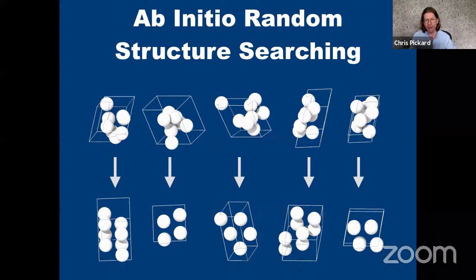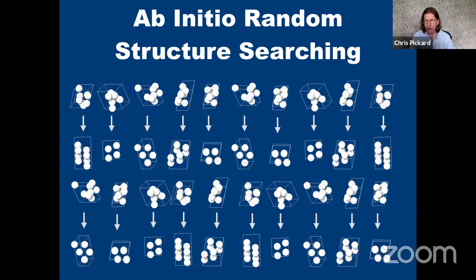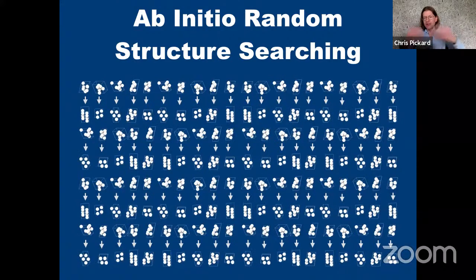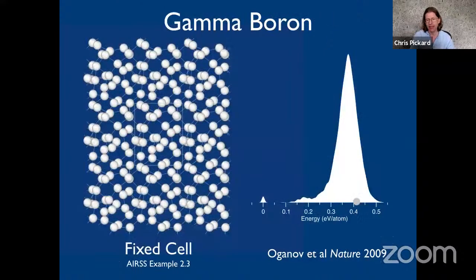So you do many of these random searches independently, all at the same time on a massive parallel computer, and then you see which of the structures are the lowest in energy, and those are likely to be the ones you might encounter in nature if you did an experiment. You might find the ground state. For example, in the case of carbon, that would be graphite at ambient conditions. But you will probably encounter diamond as well in your searches. In fact, you would. And that's a metastable phase. So again, emphasizing the importance of metastability in these calculations.